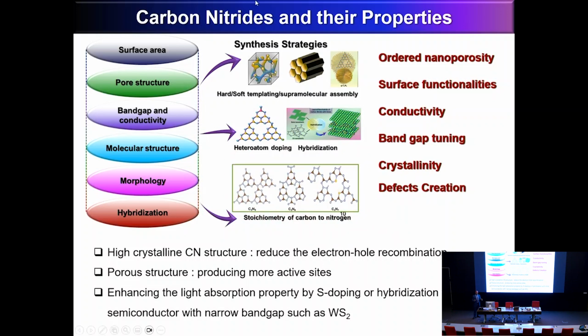Ladies and gentlemen, I wanted to tell you, so far people have predicted that carbon nitride has the stoichiometry ratio of C₃N₄. But my group has informed the scientific community that we can make a new family of carbon nitride materials with different carbon and nitrogen ratios, like C₃N₅, C₃N₆, C₃N₃, and C₃N₇. Thousands of researchers around the world are now following this research because it was not theoretically predicted, but now they have confirmed that we can have carbon nitride material with a very high nitrogen content and very high stability. So I'm going to show you first how to create the nanoporosity in the carbon nitride material.